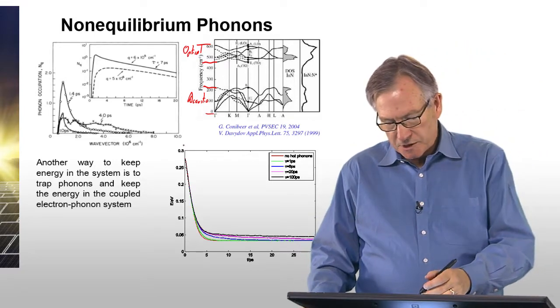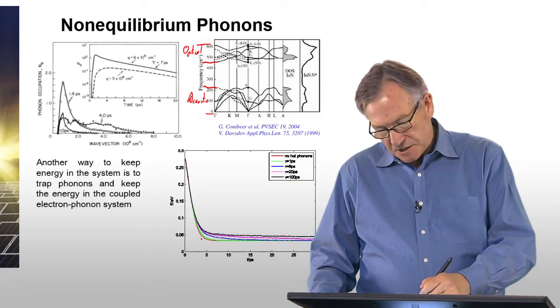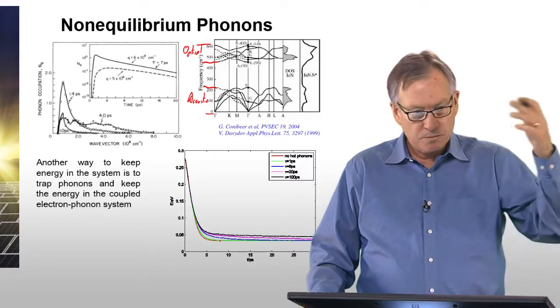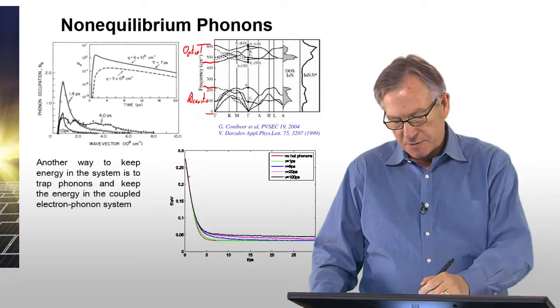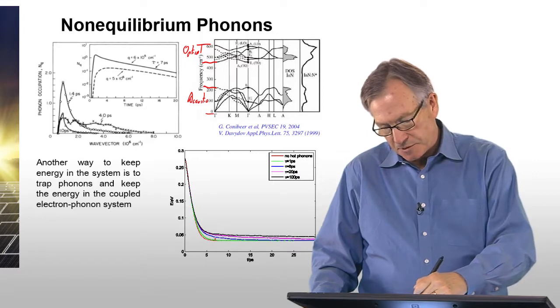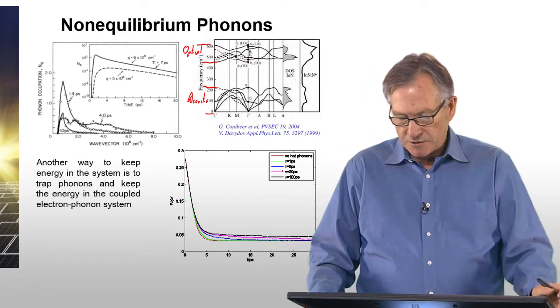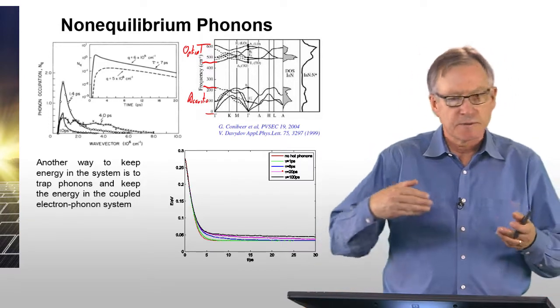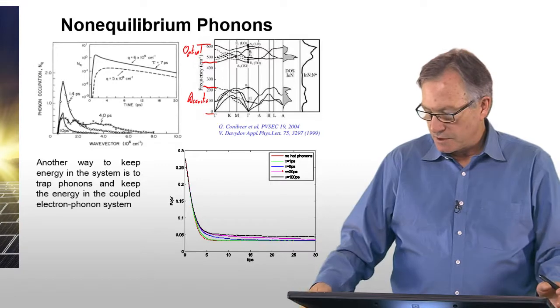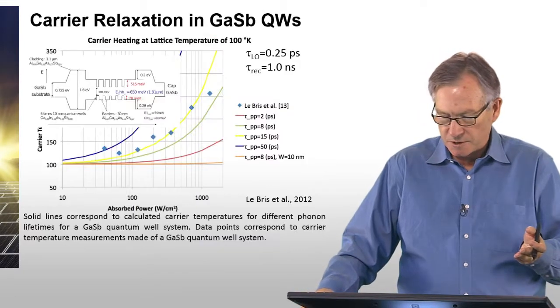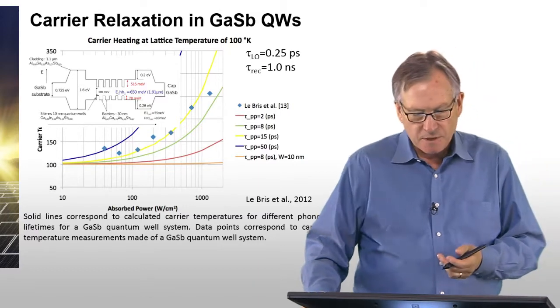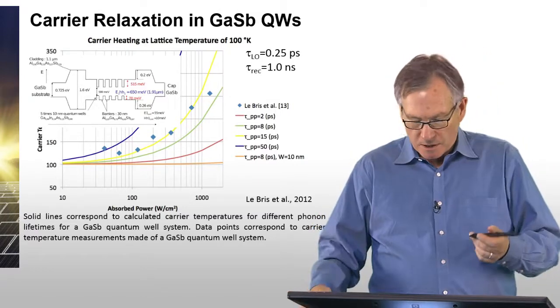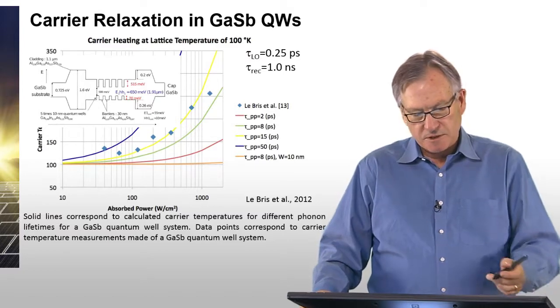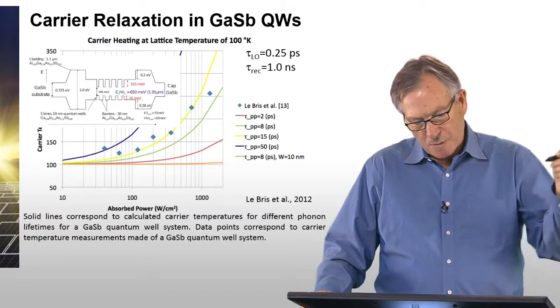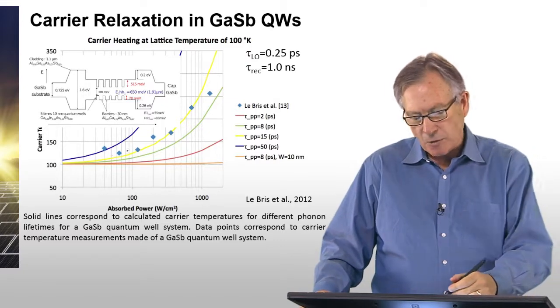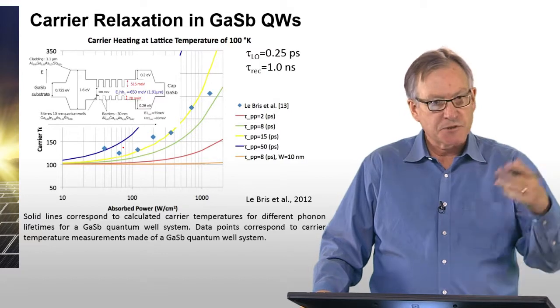And this is just Monte Carlo simulation showing that as you increase the phonon lifetime, the temperature, this is the energy as a function of time, when you create a pulse of carriers and simulate their dynamics. Instead of relaxing to the lattice temperature, they relax to a temperature that's higher depending on the phonon lifetime. So this is evidence that you can possibly with hot phonons achieve temperatures that might be useful for a hot carrier solar cell. There have been some recent experiments in which, in multi-quantum well structures, for example, the group in Paris, Le Bris group, has shown that in this multi-quantum well structure, under monochromatic optical excitation, depending on the absorbed power, you get an increase in the lattice temperature as measured spectroscopically.